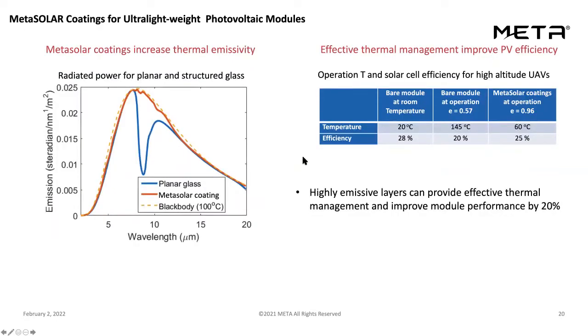As a separate approach, I mentioned improving the thermal emissivity. And for that, by using these nanostructured or microstructured elements and combining them, we were able to increase the emissivity of the solar modules. On the right-hand side, what you see is a bare module efficiency at room temperature, which is 28%. So especially for systems that are operating at high altitudes, because of the heating up, especially for modules that are lightweight, which are coated with plastic films, the emissivity is actually as low as 0.57.